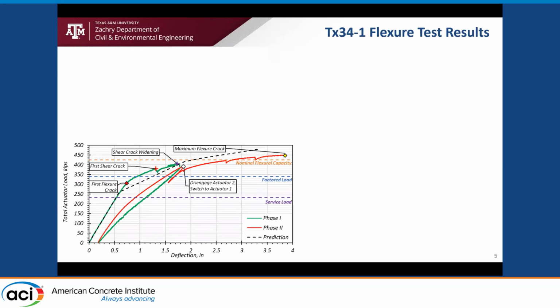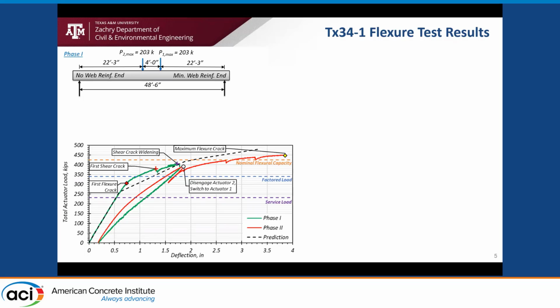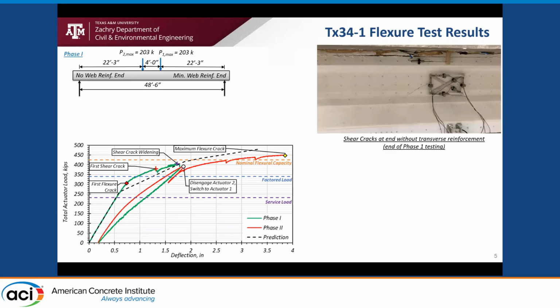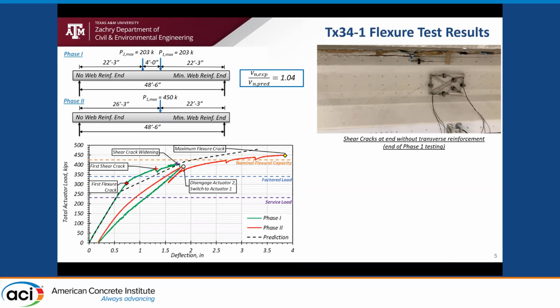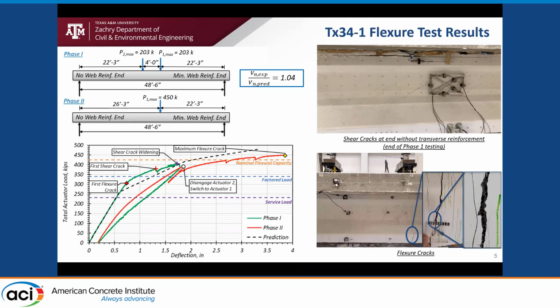The first specimen was tested and we got a pretty good capacity of 5,400 kip-feet in flexure. The first specimen was designed for a lab tensile strength of 0.7 KSI. However, for the companion field specimen, we found out that the tensile strength was 0.55 KSI. Therefore, we were anticipating shear crack prior to flexure failure, and that is what we got at the no web reinforced end. In order to preserve the beam for flexure, we decided to unload one actuator nearer to the no web reinforced end and went ahead and loaded the other end until we got flexure failure. You can see the cracks under, and the failure occurred under the loaded actuator. All the predictions were very close to the experimental values.